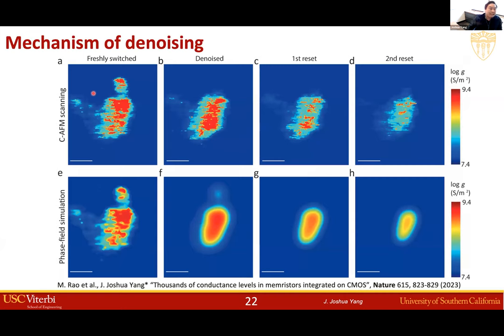Okay, so to summarize the mechanism of the denoise, basically for every RRAM switch, memristor switch, you give it a voltage pulse and you have the conduction channel start to grow, the filament start to grow. The one that grows earlier will have the time to be mature and to be complete. The one that grows later will not finish at the end of the pulse, and those end up being an incomplete channel with less oxygen vacancies in it. And it is more sensitive to charge trap nearby. And those are the trouble sites that give us the noise.